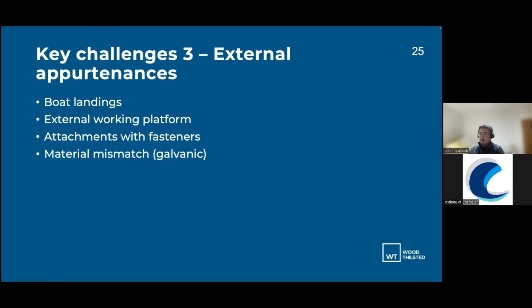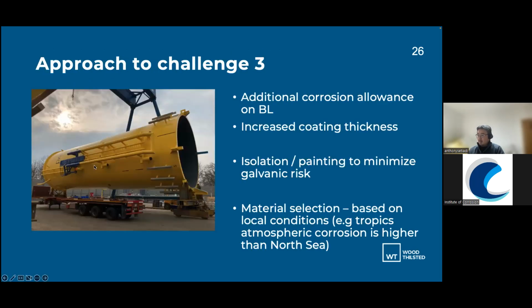The other challenge that we always face is the external appurtenances. So these are the boat landings, the external working platforms, the attachment with fasteners, so bolting, and sometimes there is quite a bit of material mismatch, which could raise the galvanic corrosion issue. So how do we deal with that? We typically go for an additional corrosion allowance to put that in, especially for these areas which are critical for people to access. We increase the coating thickness again to try to mitigate against early failures, because it's quite difficult to go out there and try to repair all of these, especially at the upper splash zone and lower splash zone.